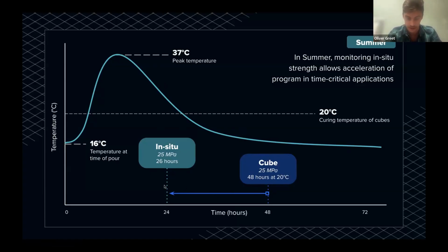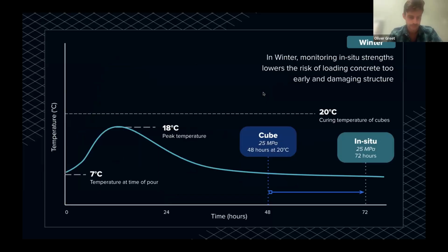In this case, a reinforced concrete slab or a post-tension slab is going to be curing slightly warmer than the samples, and therefore that's accelerated the rate of curing, reducing the amount of time. And we can see that 25 megapascals is actually achieved in about 26 hours in this case.